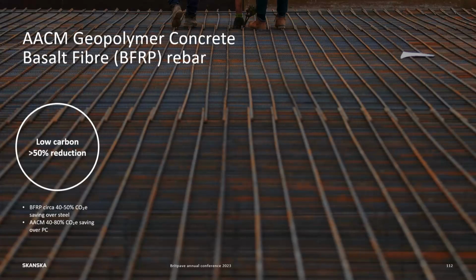Well, if you did, then the baseline of AACM concrete would give you an 80% saving. We can claim that. I'm sure Tarmac will shout that from the rooftops. But actually, the reality is going to be somewhere less because we're likely to be measuring it against a more conventional blended concrete mix that we would generally use. But the saving is still significant.